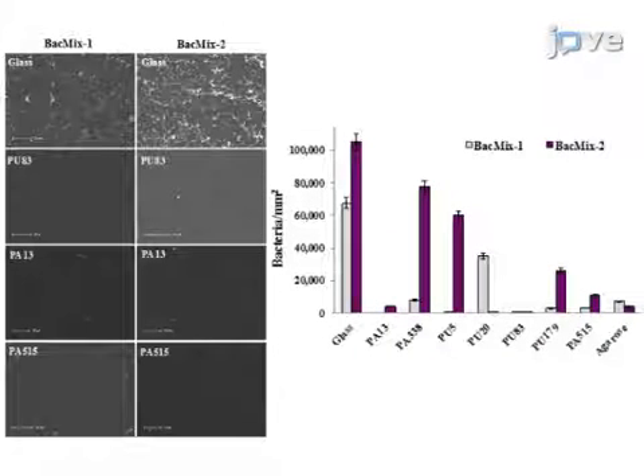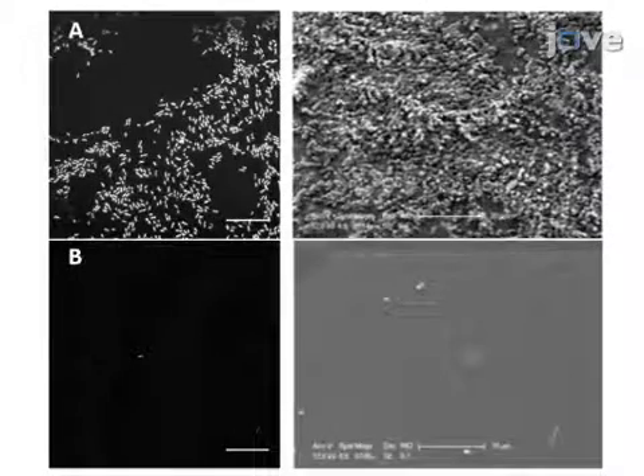Scale-up experiments to test coating larger surfaces were performed to confirm the bacteria repellent properties of 22 appropriate polymers identified. Shown here are the best performing samples used to coat glass cover slips as analyzed by SEM. These figures show catheter slices analyzed by confocal microscopy and SEM. Both microscopic methods have the benefit of allowing direct cell counts on the surface, providing unambiguous data, since reduction in cell attachment is easily visible.